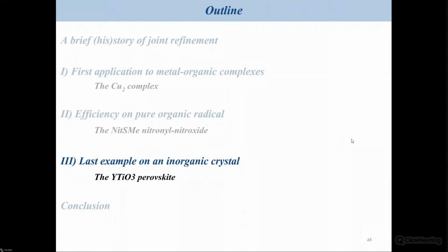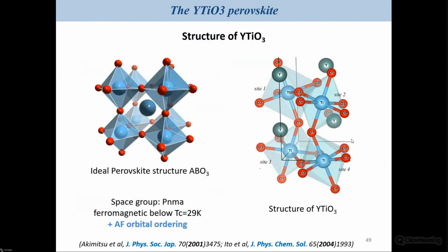Okay, let me then move to the last example, which is concerning an inorganic material, yttrium titanium oxide perovskite. It's based on the ideal perovskite structure ABO3, you can see on the left. But in that case, you have significant deformation, with angles between the titanium octahedra that are around 140 degrees. The space group of that yttrium titanium oxide is Pnma, and you observe ferromagnetic ordering at very low temperature, below 29 K, with an antiferro orbital ordering.